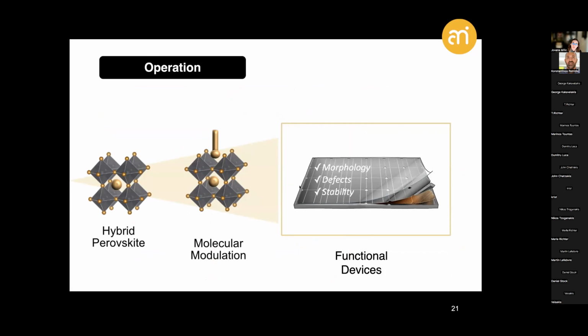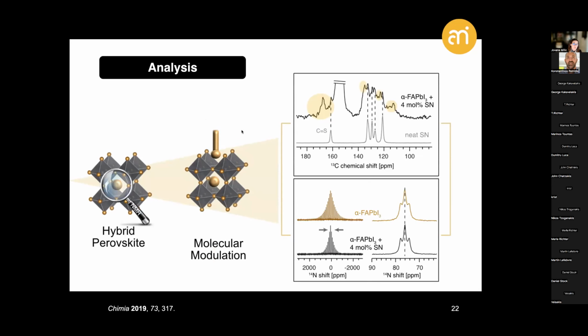Now, apart from focusing on these macroscopic properties and their role in the resulting device operation, which is very important, this has been possible by truly focusing on the atomic level interactions that enable this advanced molecular design, which was possible by complementing a number of conventional characterization techniques with the unique role of solid state NMR spectroscopy, particularly by looking into specific NMR active nuclei, such as carbon-13 or nitrogen-15 outlined here, to identify the presence of new chemical environments that can be related to the appearance of new phases, especially by comparing the characteristics of the neat samples to those of the modulated ones, their role in the structural characteristics, or also ion binding capacities that could be directly related to the intrinsic stabilization of these systems.